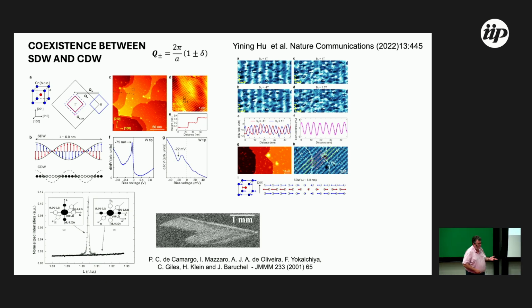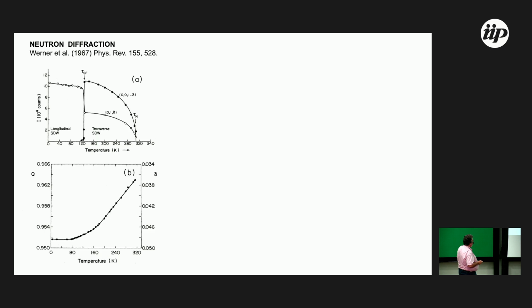Why is the single Q important? Important because a single Q produces many different behaviors in the antiferromagnetic phase of chromium. This is our first paper, from 1967, by Werner, where the intensity of the neutrons is observed as a function of the temperature of the satellites, 0 0 1 minus delta, for example. The square of the intensity of the neutrons is proportional to the magnetization of the sublattice. Okay? This is a transversal phase. This is a longitudinal phase. The longitudinal phase is not observed in this direction, 001. It is observed only at 0 1 delta, this spin density wave.